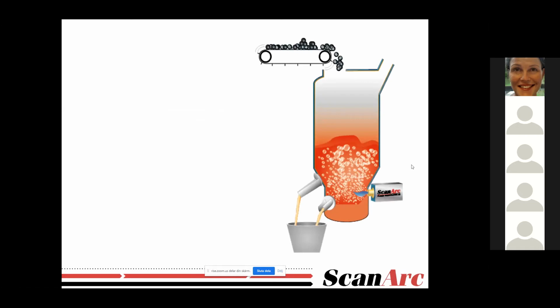Let me briefly now finally present the technology. This is an overview of the thermal reactor, and at the top of it, we add raw material to the reactor directly down to a molten bath. The process is continuous, so we have a constant molten bath and we have a constant feeding of new material, fly ashes. The fly ash melts and we use all the degrees of freedom that we have available, which is the change in pressure, temperature, atmosphere, chemical components, etc., to achieve the reactions that we require to extract metals.